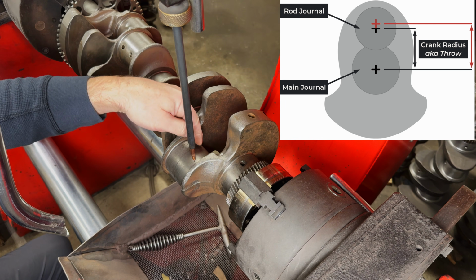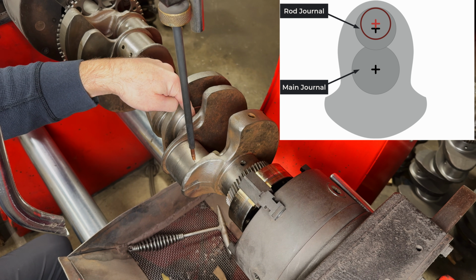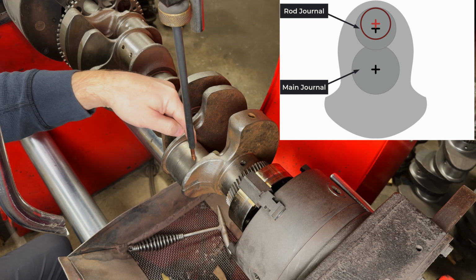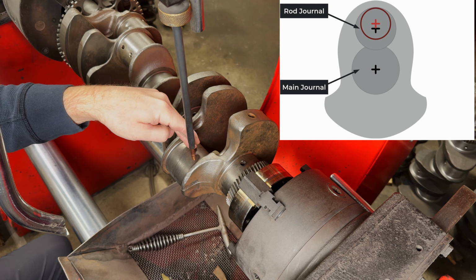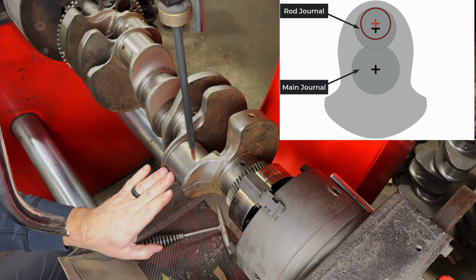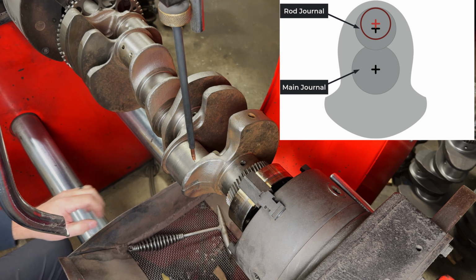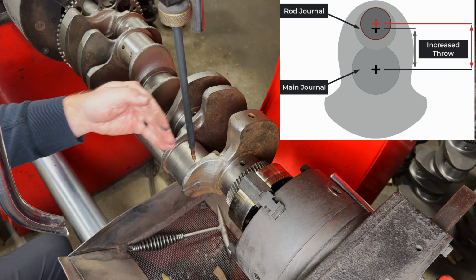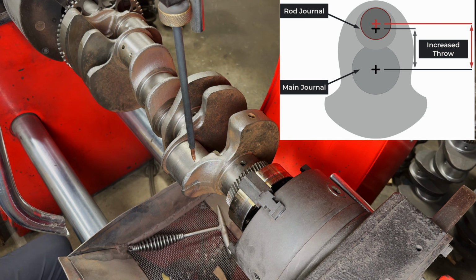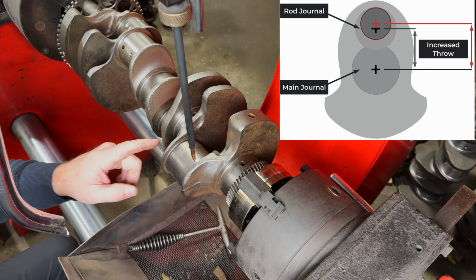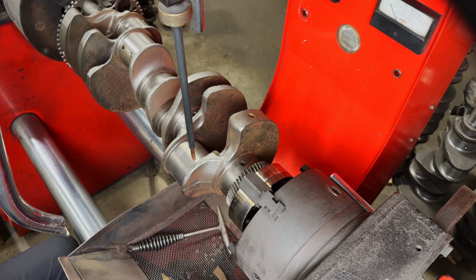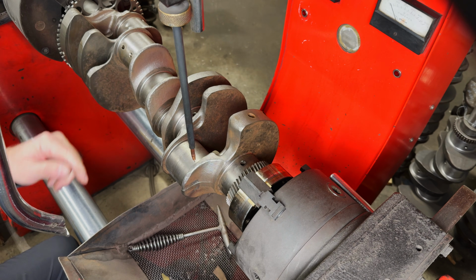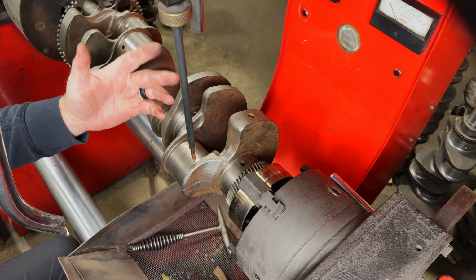In offset grinding, we remove material from the rod journal on the side that's closest to the main journal center line, and as little as possible from the far side, just enough to clean it up. That shifts the rod journal center line away from the mains, which increases the throw, which results in an increase in stroke. The downside to offset grinding is that it reduces the diameter of the rod journal, and in this case, to achieve the added stroke we want, it would make the journal too small.